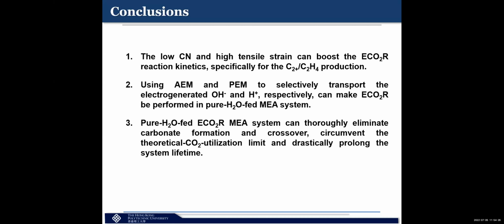So, finding a catalyst with low coordination number and high tensile strain is very important, especially for the selectivity for C2 or C2H4 production. And we proposed a new approach: just use pure water, but we have to use an anion exchange membrane and a proton exchange membrane together, so that we can enhance the transportation of the OH ion and proton. Eventually, this approach can overcome the crossover problem, and hopefully it can also lead to practical use, because the lifetime can be extended.